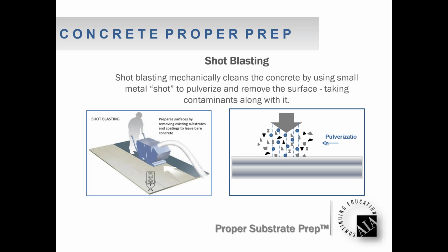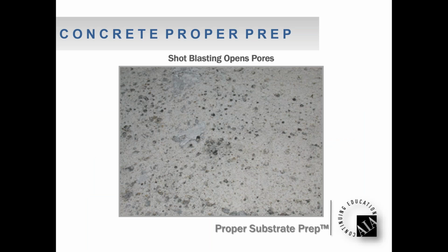Okay, shot blasting. This is a self-contained machine, different sizes, but there's a wheel inside that machine that spins at a very high velocity. There's steel shot that is thrown to the concrete at a very high velocity. It works on impact resistance. The shot hits the concrete and breaks up the surface of the concrete along with contamination. There's a vac system on the shot blaster that's equipped with a HEPA filter system. The debris is very light and gets vacuumed off. The steel shot is very heavy and it gets recycled inside that contained shot blasting equipment. So it's just a repetitive motion of the steel shot getting thrown at the floor at a very high velocity. It leaves a very clean, very open surface.